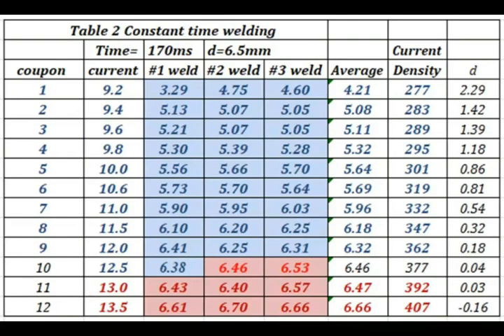This table documents a constant time, variable current experiment. The weld cap used is a 6.5 mm diameter B cap. The weld time is 170 milliseconds. The force used is 500 pounds. I started welding with 9.2 kA and the nugget diameter is less than 5.00 millimeters. At 9.4 kA I started to have a nugget larger than 5.00 millimeters. I kept increasing the current until the first expulsion that occurs at 12.5 kA. At current higher than 12.5 kA, all welds are expulsion welds.